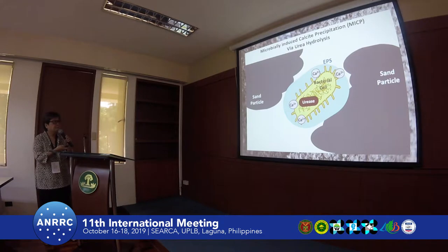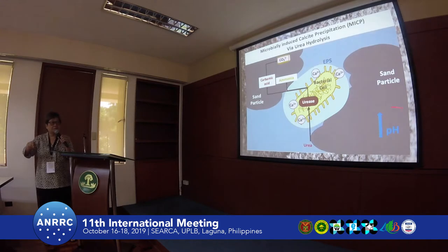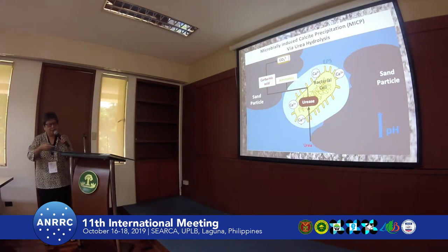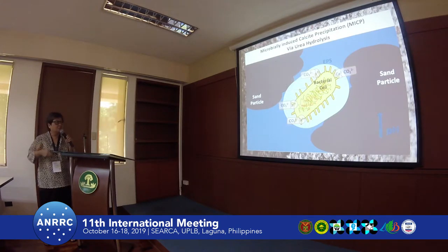Now the bacteria, on the other hand, produce urease, and the urease will convert urea into carbonic acid and ammonia. Now, the ammonia will cause the pH to rise, and the carbonic acid then dissociates into carbonate ions, which bind to your calcium ions, and you get crystallization of your calcium carbonate at high pH. So it is these crystals that will bind your sand particles together.